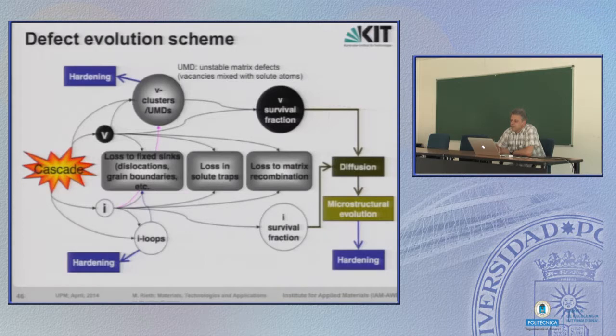Then interstitials can form loops, dislocation loops. These dislocation loops, again, can annihilate by the reaction with other dislocations or at grain boundaries. The same is true for vacancies. Vacancies can also form clusters, and these clusters can interact in another way. We come back to that later.